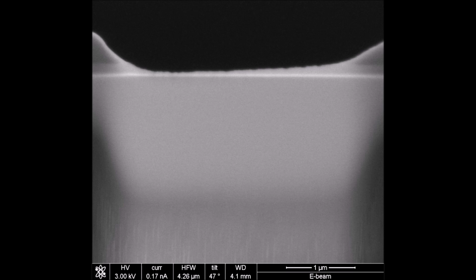And so you can see very clearly that really thin, bright layer at the surface is still intact, and I have just a little bit of protective platinum still on top of it. And that's exactly what you want when you're making a lamella, where you're trying to preserve that very, very near surface region. And so at this point, you don't want to do any more imaging of the specimen in the FIB. You want to turn everything off, take the sample out of the FIB, and go straight to the TEM, if possible.